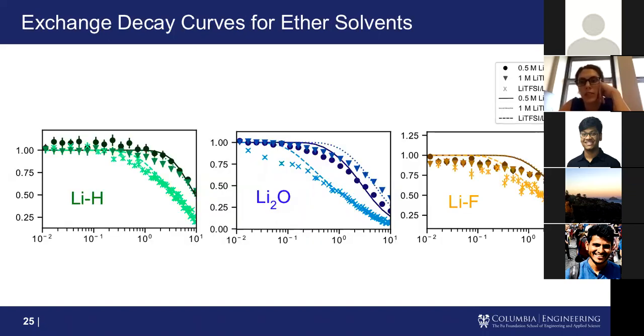So this is what the data looks like whenever we actually look at the decay. How we run this experiment is we vary the time that we let our lithium ions diffuse in the experiment, and then we can fit that to extract our diffusion coefficient. All you have to take away from this data is that if something decays more quickly, then it has a faster diffusion coefficient. These little X's here are all for the nitrate containing sample. So you can see for every single SEI component, we get faster lithium ion diffusion whenever we have the nitrate present. That tells us something about the mechanism of what the nitrate is doing. It's helping lithium ion conduction through the SEI.